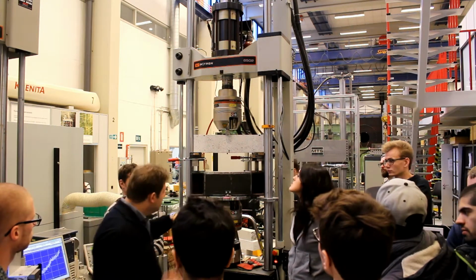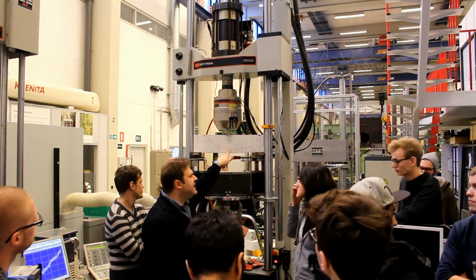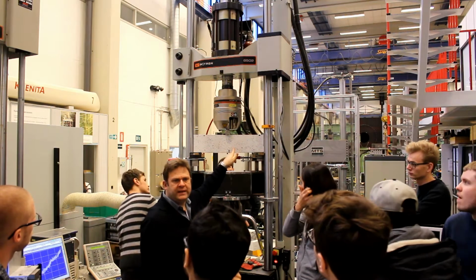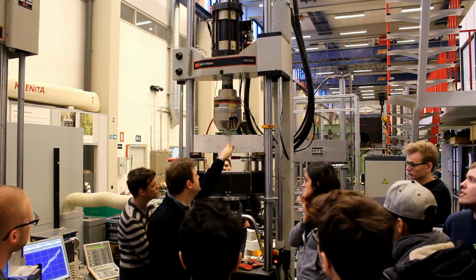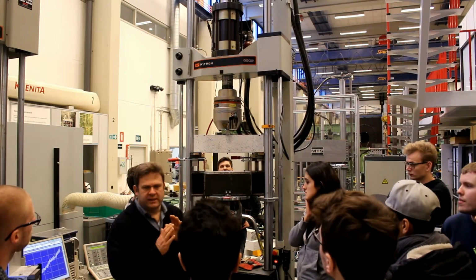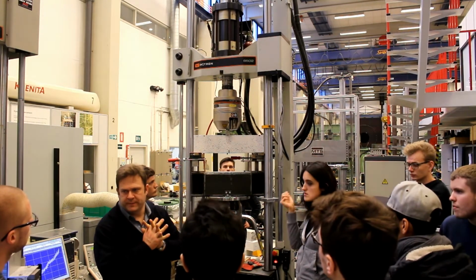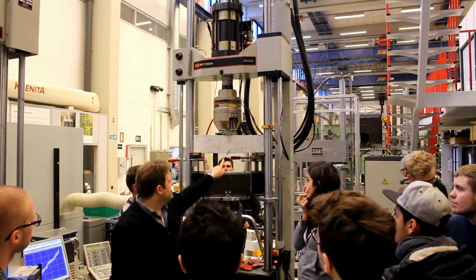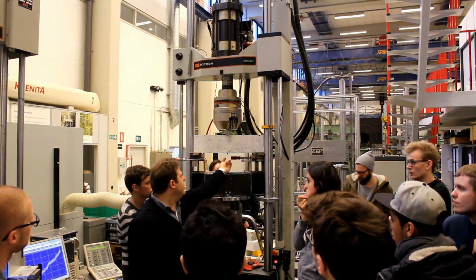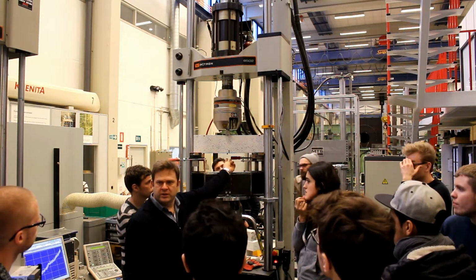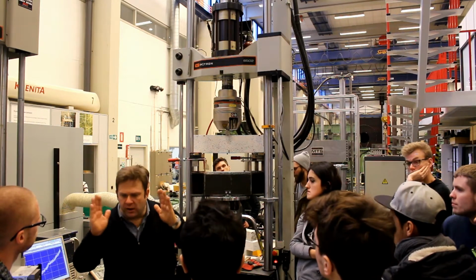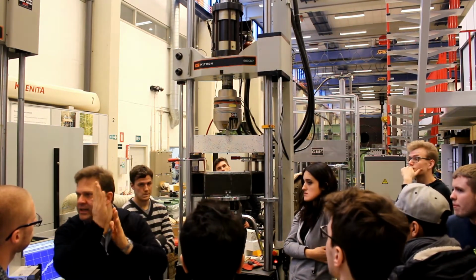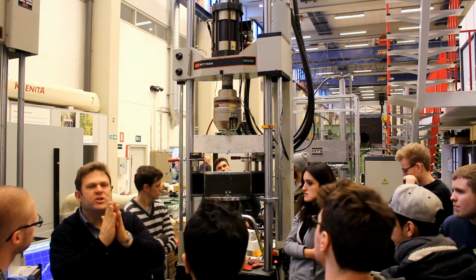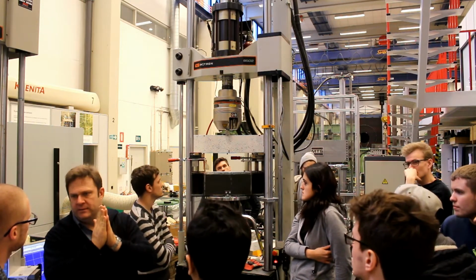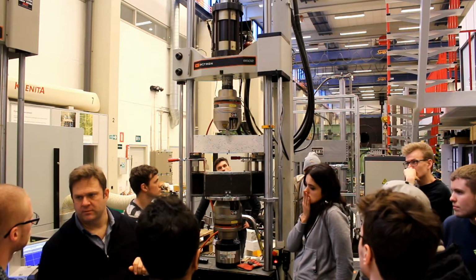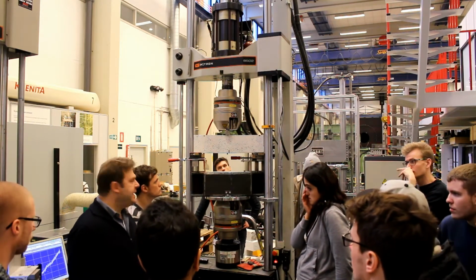You can see now that our idea of having one crack only does not really apply. There are several cracks in parallel that are forming in this material. But since we had the notch introduced and we are measuring the opening of that notch, we would lump these different cracks together into a measurement of one crack opening through this notch. Okay? Any questions?